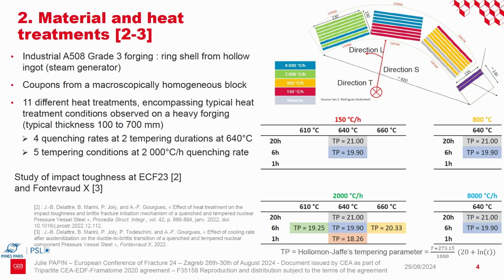We chose to study 4 quenching rates at 2 tempering durations at 640 degrees, and 5 tempering conditions at 2000 degrees per hour quenching rate. The study of impact toughness was presented at the previous edition of ECF and at Fontevraud 10 in 2022.